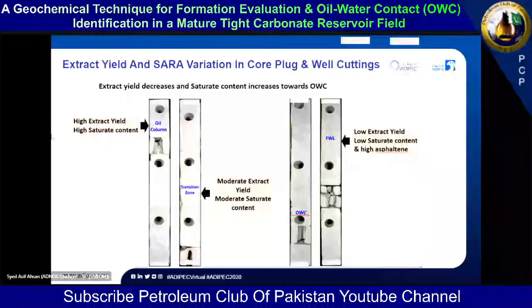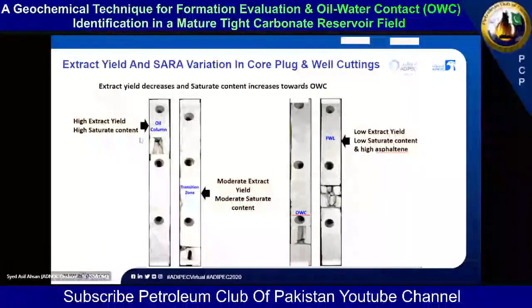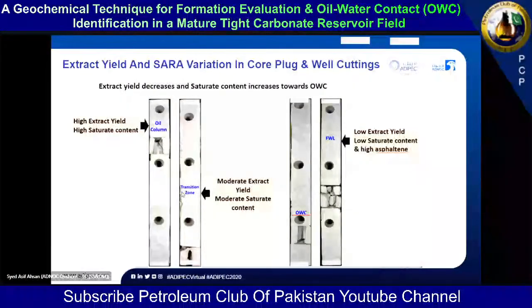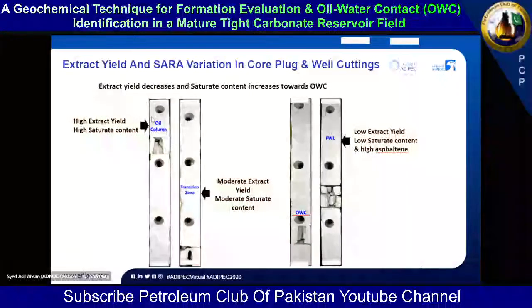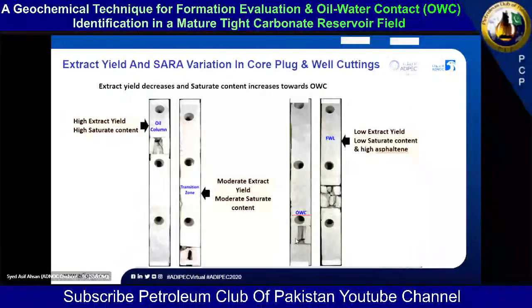So within the transition zone, and our reservoirs are mostly from the transition zones, you have a lower amount of extract yield and lower amount of saturates compared to the proper oil column. And any sample coming from below the oil-water contact will be very high in asphaltene and resins, and very low in saturate and extract yield.